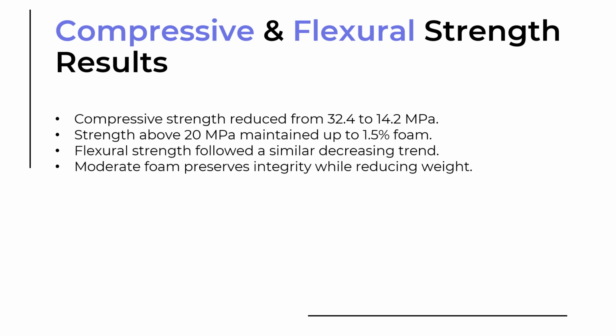We found also that the compressive strength was reduced from 32 to around 14 megapascal, and strength above 20 megapascal was maintained up to 1.5%. And also we saw a trend of reducing flexural strength, and moderate foam preserved integrity while reducing weight.